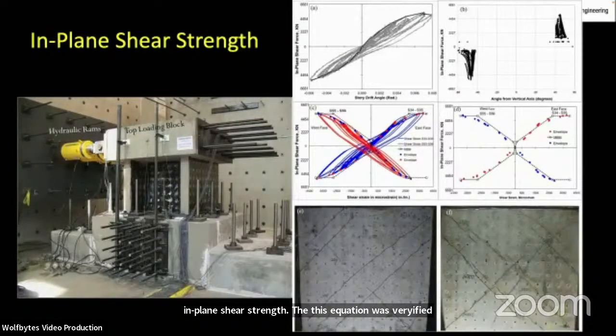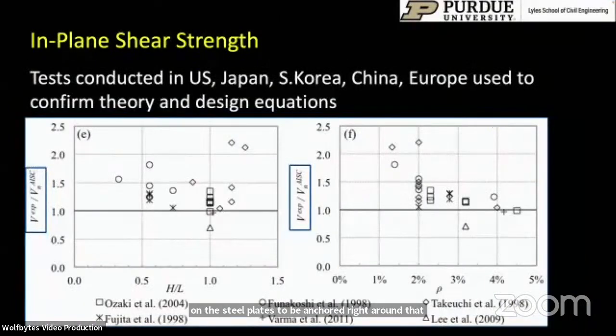Here I'm showing you a comparison of the trilinear curve with the backbone of the experimental data that we obtained from the in-plane shear behavior of this stocky or short squat shear wall. Besides that, after the testing had been completed, we removed the steel plates in order to examine that those 45-degree cracks were indeed forming, and we also identified the principal strains that we were measuring on the steel plates to be anchored right around that 45-degree point in both directions.